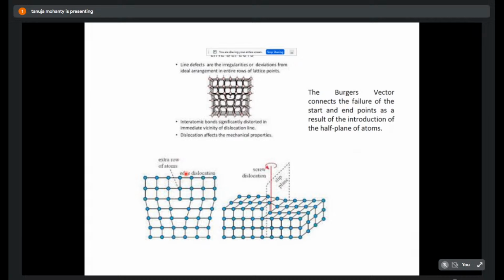This type is called an edge dislocation, because this dislocation occurs due to an extra row of atoms introduced into the crystal. And there is the screw dislocation. A screw dislocation is where you have a plane, one above the other, and you have a slip plane. So they are not at equal height. Here you can say it is like a slanting mode, with a step difference. It is like a screw, because when a screw goes, it is never in a planar position.